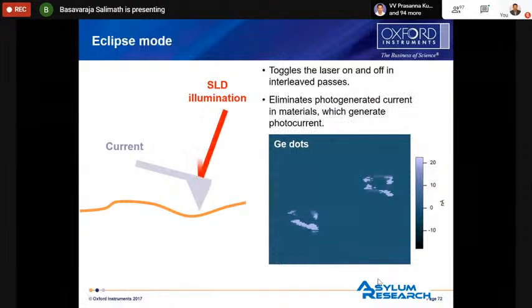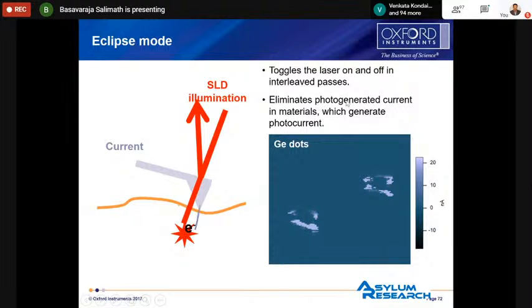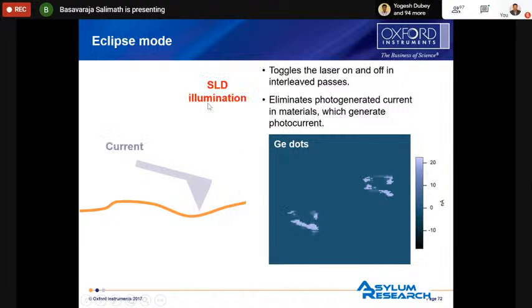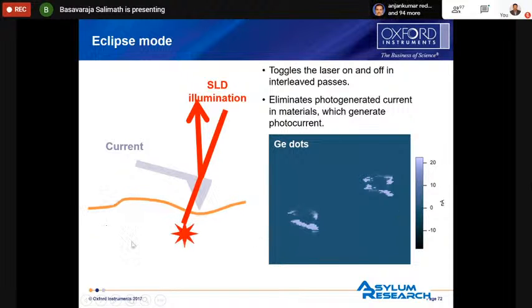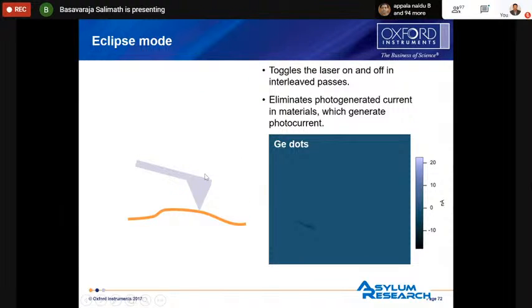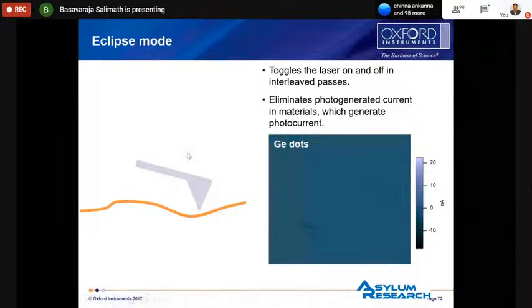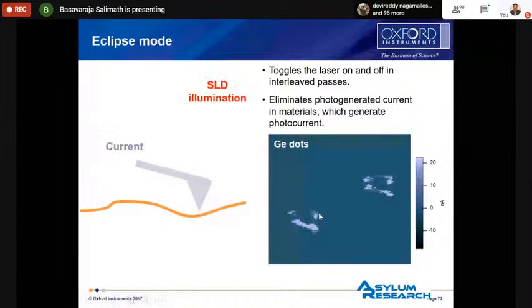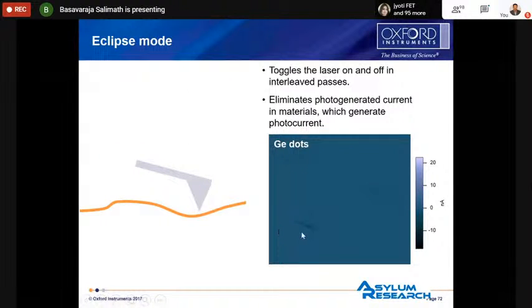And also, if your sample is generating any kind of photocurrent, because as we are using some laser, a small amount of laser may fall onto the sample, that may generate some kind of photocurrent in the image. So you want to avoid that. We have eclipse mode. In the eclipse mode, initially it will do one scan with the laser on, and you get the surface morphology. After that, the same line will be scanned one more time with the laser off, to avoid this photocurrent. So it scans the same line two times: one time for topography, and another time, by switching off the laser, for the current image. You can see this is with the laser on, we can see some photocurrent. This is with the laser off, we can see a very small amount of current at this place only, not at these areas. Like this, we can avoid photocurrents in the image.